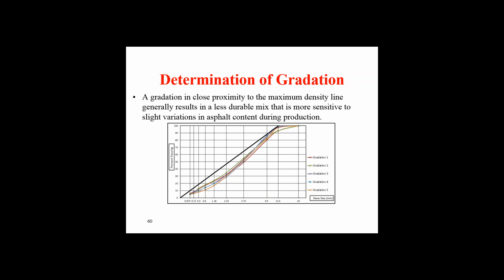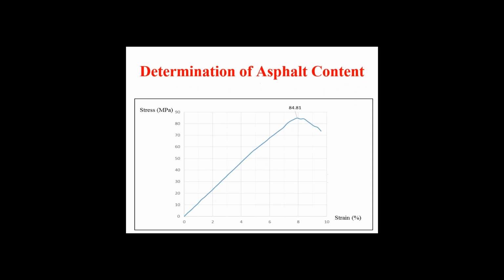But we cannot rely on the closest one. Right? Some of the particles, when it's close to the highest density, then you have some kind of stability problem. It's easy to lose stability in there. And we use this computational methodology to mimic, to simulate the compression test. And then in this case, we can reach different strain rates and reach the peak stress.